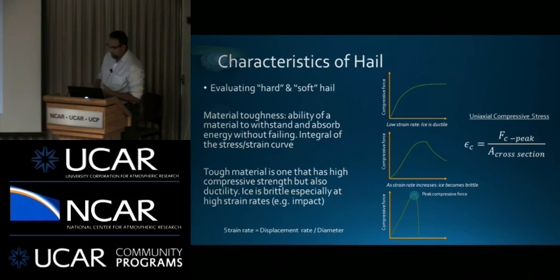So ice, if you're slowly compressing it, it will be very ductile, meaning it will want to compress. Ice starts to melt a little bit and compress and hold its shape. But as you increase that displacement rate and so forth, strain rate, you'll get a brittle failure. It'll essentially shatter, so cracks will start to propagate through it, and you'll get a very sharp peak if you look at the applied force versus time curve, and that's this bottom conceptual graph. You can record that peak, and that's essentially the peak load that that object could support before it failed.